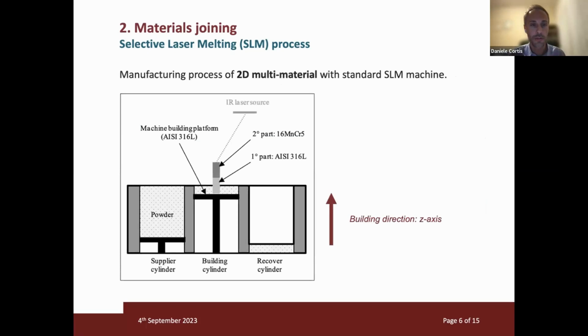So how can a normal user build a bi-material along the building direction, or a functionally graded material, with this standard machine? The procedure is very simple. Of course, first the user has to build the standard specimen, the standard component, on the building platform of the machine. Then they have to replace the powder material, realign the building platform with the recoater of the machine, and then build the second part above the first one. So it's very, very easy to say with these words, but of course it's necessary to fine tune the parameters of the machine, especially at the interface, because some materials are not so easy to join together.